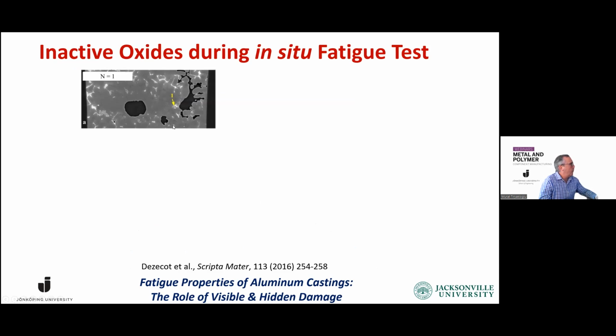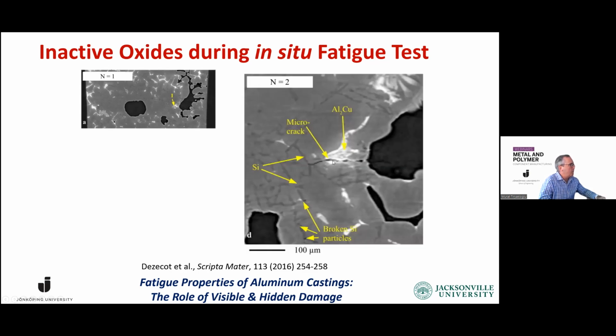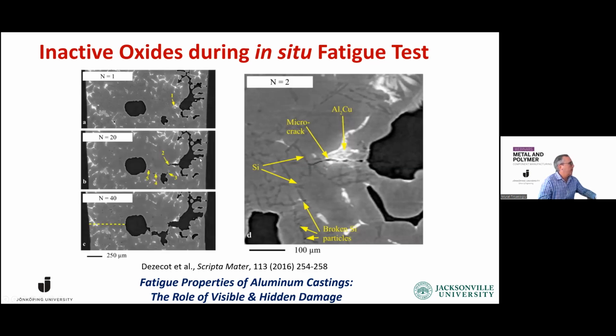Here you see two pores, but at the first cycle, you're going to notice that a hidden oxide opens up and presents itself. It's not at the point of the highest stress concentration. This crack opens up right away at the first cycle at a high temperature, where you would expect the metal to be very ductile and absorb this kind of energy, but it doesn't. It opens up. And then after a few cycles, it links to the main pore. Many other oxides open, all the way from very small to large. And all the crack has to do is to follow those opened up damage to cause the final fracture.